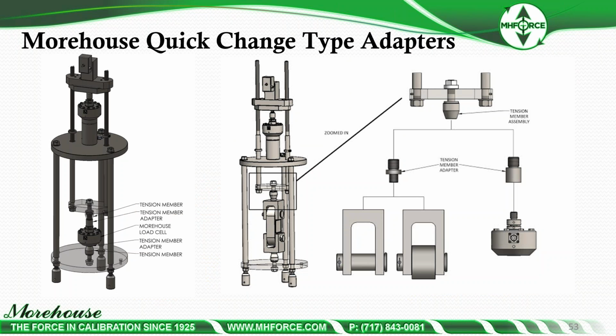So here are some pictures of adapters. We've adopted ISO 376 here. If you look at this, this is our quick change tension member adapters. In most cases, there's a spherical here, and there's a spherical down here, here, and here. Here it's shown with a clevis, probably an ED dynamometer, where if you've seen our other webinars, you know the pin size in these makes a huge difference. But in any case, this adapter system, not only for load cells, but for clevises set up for other dynamometers, crane scales, whatever, will keep that line of force as pure as it can be.